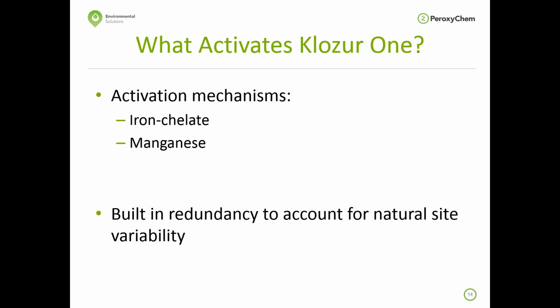Manganese, permanganate is actually manganese 7, but as it goes to more reduced manganese oxidation states, the reduced oxidation states of the manganese can also serve to activate persulfate. So for example, as manganese 7 is reduced to manganese 5 and manganese 6, it can then react with the sodium persulfate and activate the sodium persulfate, forming different radicals. We liked adding multiple different transition metals to essentially build in a little bit of redundancy into the system, thinking that in some situations iron might serve as a better activator, and in other situations the manganese may.